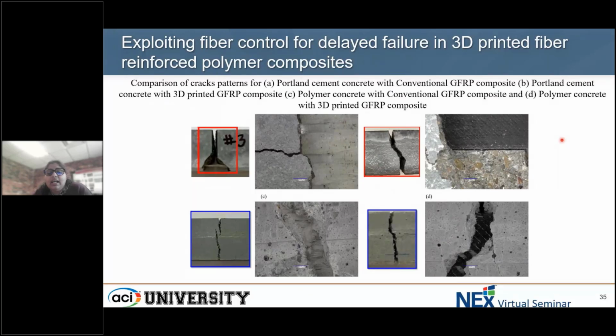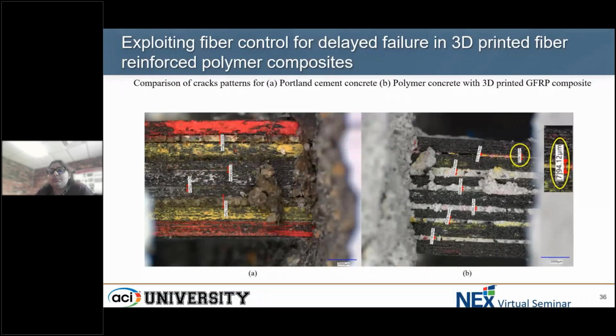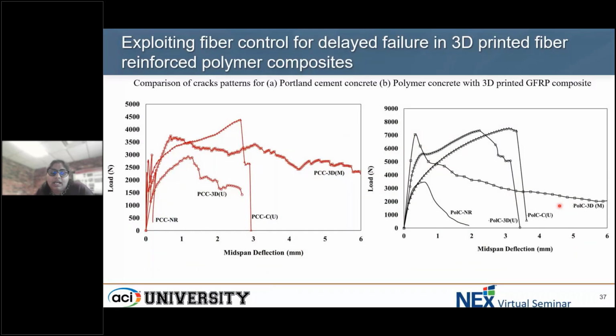So one of my students here studied these composites in cementitious and polymeric cement mortars, and we observed that there is definitely good interaction between these 3D printed composites and both these types of concretes. Especially in terms of cementitious versus polymeric concretes, we saw that cementitious concretes cannot necessarily get into small gaps. But if you take a fully debonded composite, which behaved the best in terms of strength and ductility, this polymeric concrete can actually seep into these gaps of about 94 micron even and allow that shear transfer to be so efficient that, if you look at the ductility behavior, high strengths are possible and a delayed failure strain, in order to achieve some of the ductility targets that there are with conservative standards.